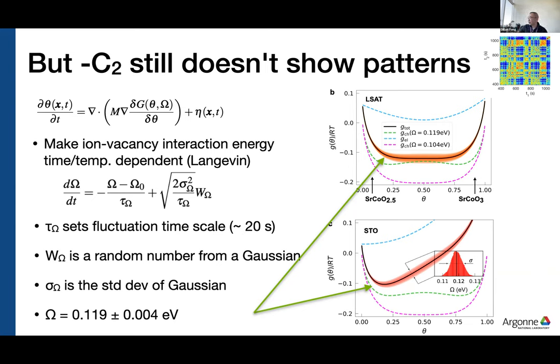W is a random number coming from a Gaussian distribution, and I'm showing this Gaussian distribution on the bottom right. Sigma is the width or the standard deviation of this Gaussian profile. And omega, like I showed on the previous slide, was found to be 0.119 eV to give us the right time scale. And so they found that they had to make this time-dependent interaction energy where omega is fluctuating between 0.119 and that plus 0.004 eV or that minus 0.004 eV. So that is the red halo around the black free energy curves that I'm showing on top and bottom.